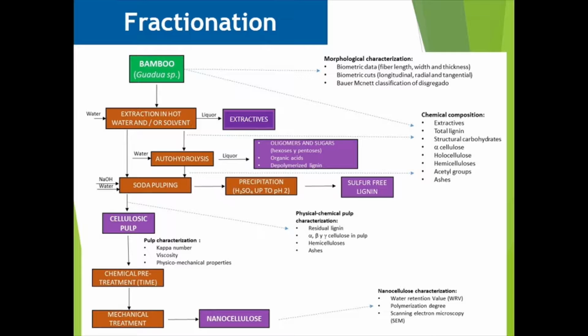The resulting pulps were physically and chemically characterized by Kappa number, alpha, beta, and gamma cellulose, residual lignin, degree of depolymerization, water retention capacity, and crystallinity. Then, a chemical pretreatment, TEMPO, and a mechanical treatment were applied to both pulps to obtain nanocellulose, which was characterized by its carboxylic groups content and viscosity. In each of the liquid streams, we obtain hemicellulose and lignin together, which can be studied and valued to obtain another product.